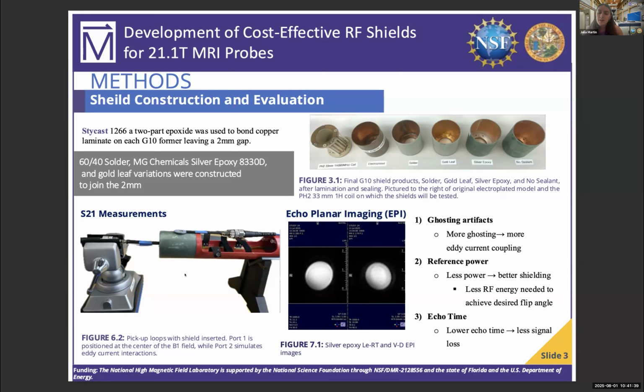In the 21.1 Tesla magnet, I use echoplanar imaging sequences to evaluate three main parameters: ghosting artifacts, reference power, and echo time. EPI features fast switching gradients, and every time the gradient is turned on and off, it generates eddy currents faster than normal sequences.